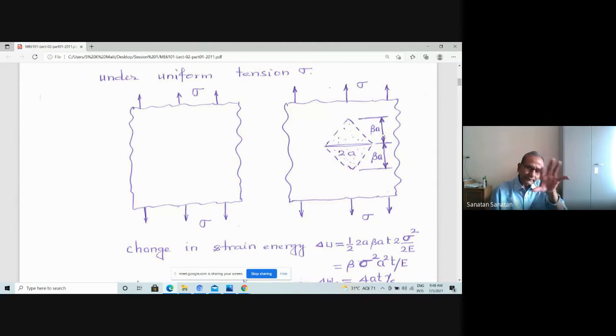So in the material, as you load it, it is strained, and as the crack extends you are creating surfaces, and you have to supply surface energy. Where does it come from? The crack is creating a stress-free region, that material becomes stress-free, and therefore it loses strain energy. So two energy forms are at play during crack extension: the material is losing strain energy, and at the same time it is supplying the surface energy. So he made it very simple: crack propagation takes place in the presence of two forms of energy, one is strain energy and another is surface energy.